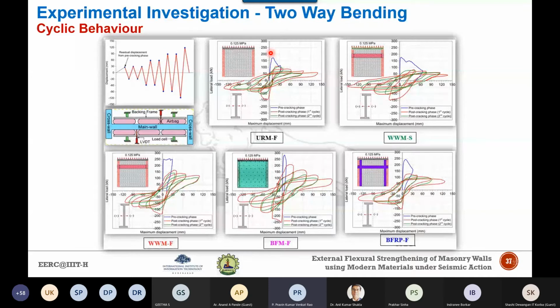On the other hand, the post-cracking hysteretic loops represent cycles of different amplitudes applied starting from the residual displacement of the pre-cracking phase. Here it can be observed from the figure that the load displacement behavior of all the walls has 2 distinct phases. The strength during the pre-cracking phase is much higher, shown in blue, and it reduces drastically in the first cycle of the post-cracking, whereas the degradation in the successive cycles is relatively gradual in all the cases.